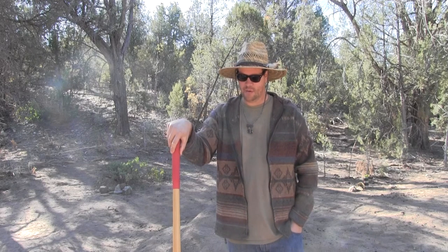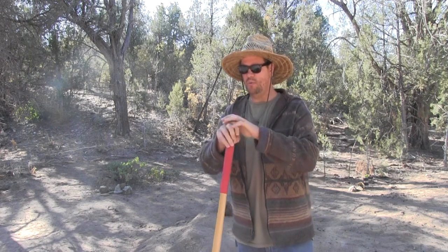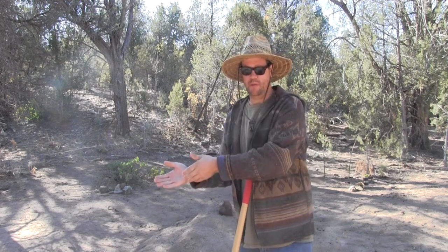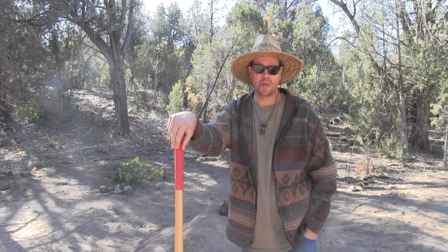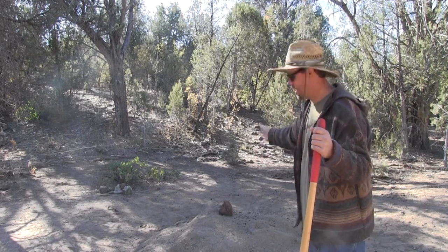It's the next day and we gave it overnight to let them sit. Technically we could have pulled the pots out that night, but the longer we wait the better. We're on a short time frame, so I'll unearth this kiln. Keep in mind the kiln is still very hot, so once I start removing dirt and get into the pit structure, I'll let the pots sit in open air before removing them to slowly cool and avoid micro cracks forming.